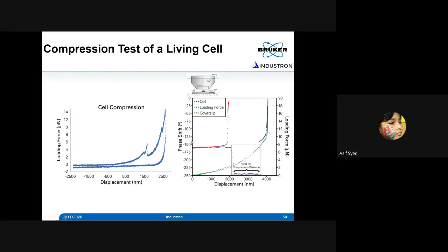If you look here, the phase shift as a function of approach: when there are no cells, when you make direct contact with the glass slide, the phase shift shoots up from minus 160 to 0 degrees. But when there is a cell, the phase goes down because of the attractive forces. The phase shift moves in the other direction, and you can see a big jump. Now we know that the tip is getting attracted to this cell structure, which we can see through the phase shift. So we know that we are making contact, and then it compresses the cell, and then you can see that it comes back.